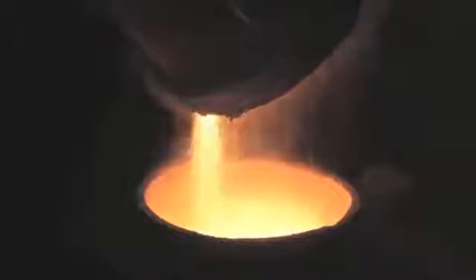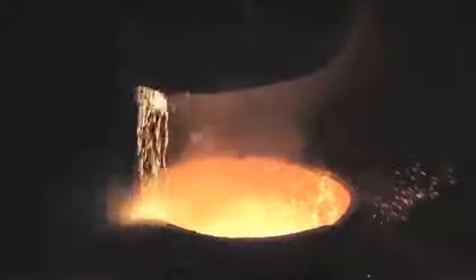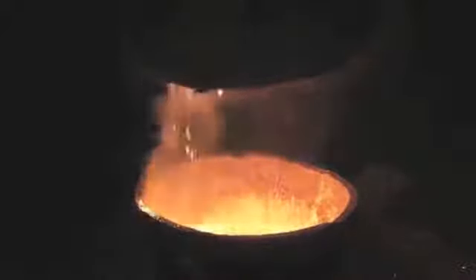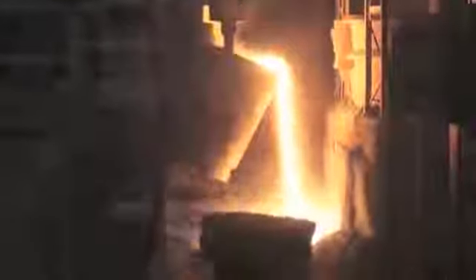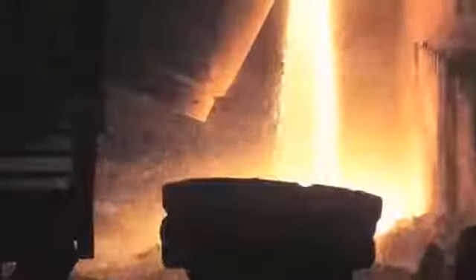SDI is also making iron-rich units with a pioneering process at Mesabi Nugget in Minnesota. Both SDI and Mesabi use iron-making methods that are far more eco-friendly than traditional blast furnaces. Mini-mills use electric arc furnaces, or EAFs, which require much less in the way of natural resources versus traditional blast furnaces. For every ton of steel produced by SDI, we eliminate the need for 2,500 pounds of iron ore, 1,400 pounds of coal, and 120 pounds of limestone. And we use significantly less energy in the process. The EAF process also produces 67% less carbon equivalent emissions. In addition, 95% of our scrap comes from within 250 miles of our plants.